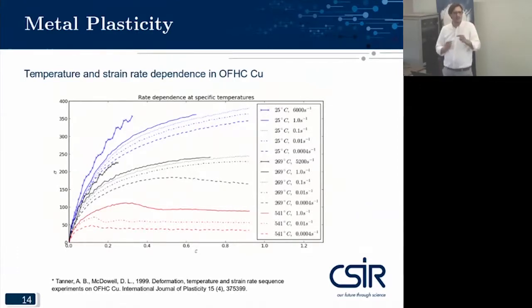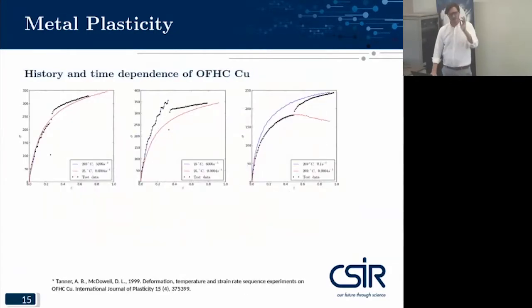As soon as you add atoms of different shapes and sizes, these impinge on the grain boundary moving, so things get far more complex, once you consider the melting temperature of something like copper versus cobalt within a specific alloy. More importantly, you can see the rate dependence of plasticity. In this specific case, you would deform a material and then change the deformation rate or temperature. And you can see that it doesn't simply jump from one curve to the next. It has a history effect.